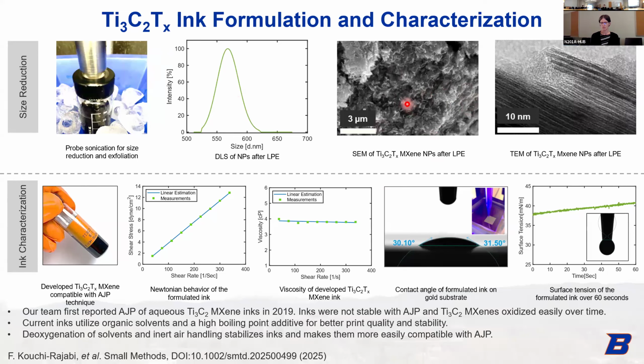And you can see we use a co-solvent system. I think it's ethanol, water, and ethylene glycol for this work. So we did the ink characterization. You can see the shear stress versus shear rate, with a viscosity of 4 centipoise. That works really well for the aerosol jet ultrasonic atomizer. And we have a nice contact angle on our printed gold, which we're using.